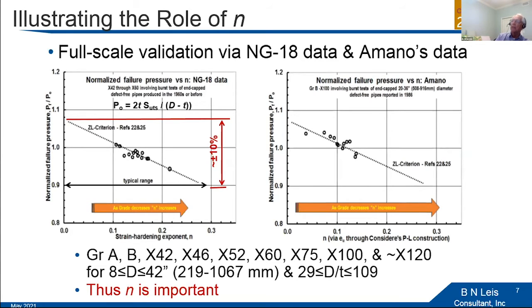These are test data for defect-free pipe across a range of materials and pipe geometries. And what you see in both cases here, two different data sets, is that the data follow a clear trend as a function of the strain hardening exponent. And you see it here, there's a swing of roughly plus minus 10%.